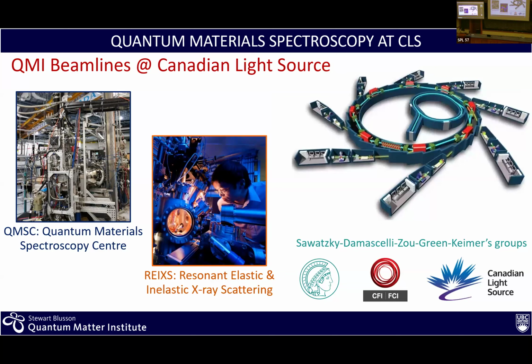There is instrumentation around the world. Synchrotrons are a natural place to do this, because you can tune the photon energy from the XUV into the X-ray. So you need high enough photon energy for the experiment. These are beam lines that we build at the Canadian Light Source for angle resolved photoemission or even resonant X-ray. Eduardo here has made big use of both facilities. And we also have facilities, of course, at UBC in-house. And so these are the kind of places where we do the experiment.